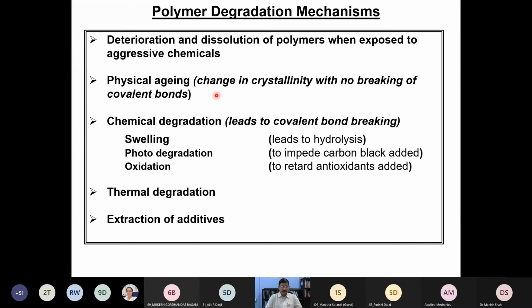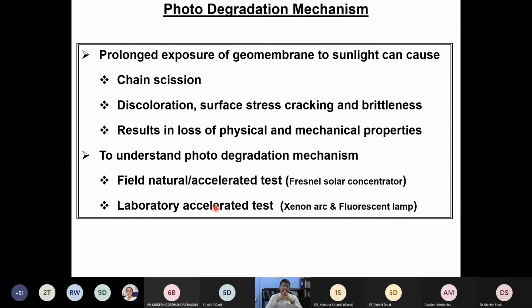Among all these, even though these two are not really relevant, let me talk about how photodegradation happens. This is when a geomembrane is exposed to sunlight as part of a cover liner, where it is not supposed to be. Or sometimes, even if you construct a basal liner at the bottom of a landfill, many times people either do not cover it with the drainage layer, or do not place waste as soon as they construct. Invariably, the geomembrane gets exposed for periods from 2 to 3 months to anywhere up to 5 to 10 years. Sometimes the cover liner is not properly covered with a vegetative layer, and is most of the time exposed to sunlight.